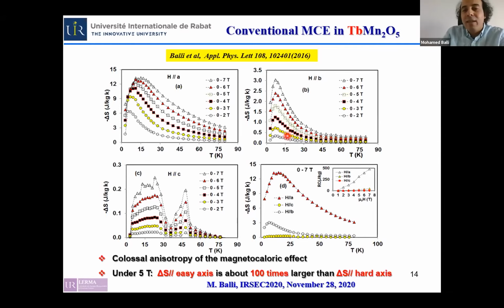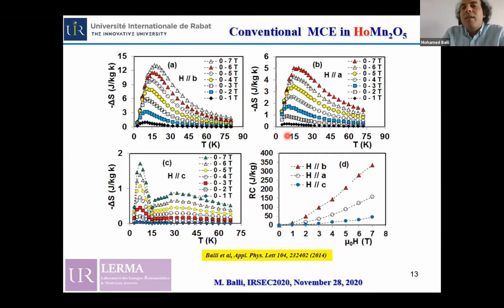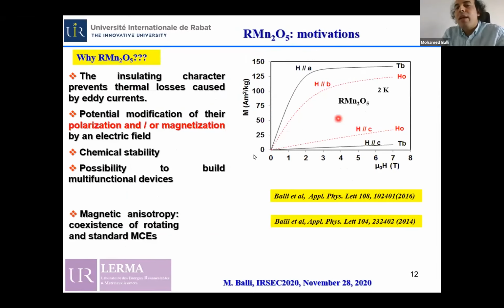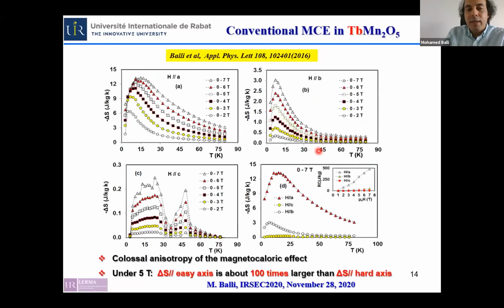As can be also seen clearly in this figure, the terbium compound involves a giant anisotropy of magnetization. This would also explain the marginal value of the entropy change along the C axis.